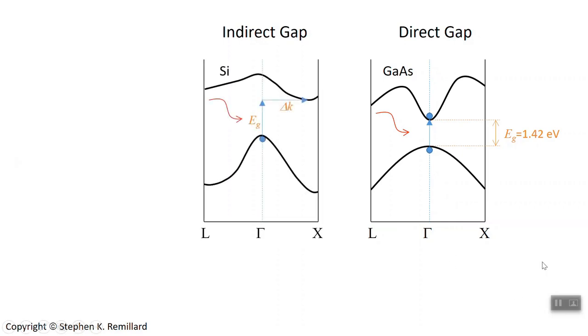But what about silicon? It isn't only the workhorse of semiconducting electronics. Silicon is also an indirect semiconductor. The conduction band minimum is close to the X point in the reciprocal lattice. Meaning if an electron is going to transition from the conduction to the valence band, it has to not only undergo an energy change in order to get from one band to the other. It needs a momentum change. It needs impulse.